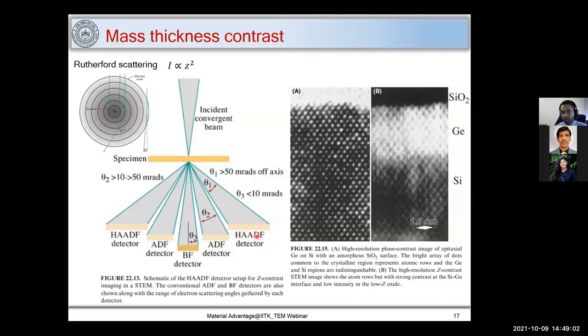Now, what is the utility of these HAADF detectors? Here you see a classical case where germanium and silicon are grown on SiO2. Germanium and silicon have the same crystal structure, that is diamond cubic. So here you cannot distinguish Ge and Si, but if I do this HAADF detection, you can see that germanium has a higher atomic number, so it looks brighter here because intensity is directly proportional to Z squared. That is what we have seen. So germanium will be brighter as compared to silicon, and thus we can differentiate germanium and silicon.